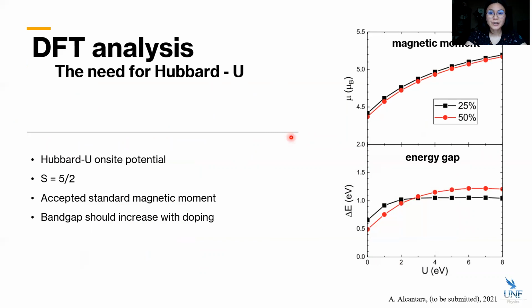So Hubbard U works by creating a well around the atoms, so more potential for the system is created. And without Hubbard U, there are two issues that arise. First, the magnetic moment is way too low. It's at a spin of 2, and it should be at a spin of 5/2. And then the band gap is also very low, and experimentally speaking, the 50% should be higher than the 25%.